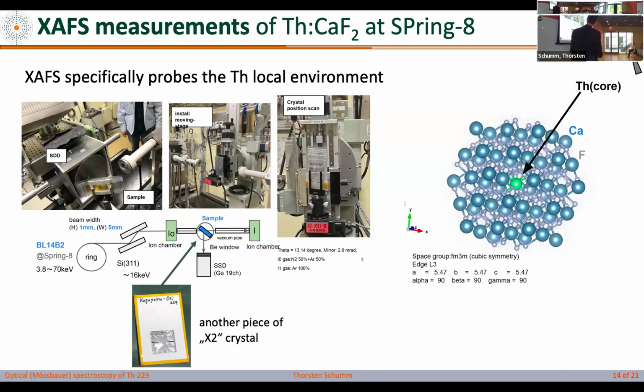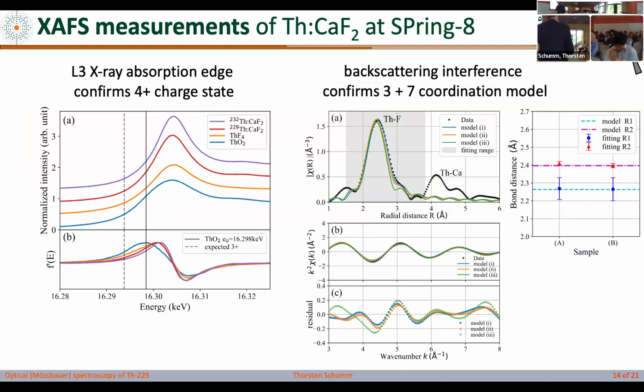So the X-ray just goes through, and when it sees the thorium, it starts to ionize the thorium inner shell electrons. And this is, we didn't invent that either. This is just reading another book and using techniques that very clever people have developed over the years. And by looking at which exact energy this L-shell ionization takes place, we can learn something about the charge state of the thorium. And we find that, yes, it is indeed 4+, so that, yes, it really gives away the outermost 4 electrons.